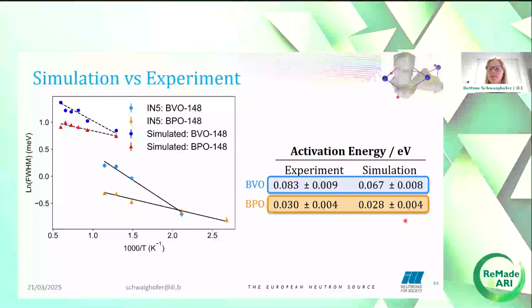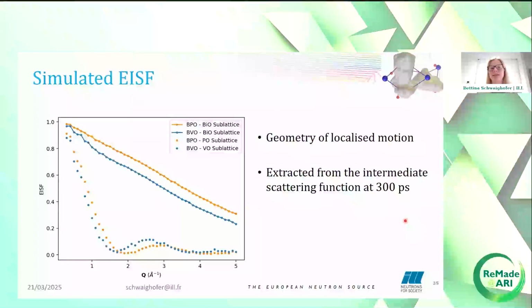We therefore tried to analyze the simulations in more depth, which was not possible with our experimental data. For example, we could look at the elastic incoherent structure factor, which gives the information on the geometry of the localized motions. To make the analysis a bit easier, we separated the oxide ions into oxide ions originating in the bismuth oxygen sublattice and those originating in the dopant sublattice. And a very clear EISF trend for those originating in the dopant sublattice can be seen.